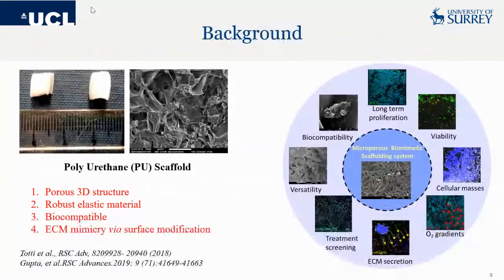So in our group at the University of Surrey and now with UCL, we have developed a polyurethane scaffold-based model of PDAC. These scaffolds are prepared by thermal-induced phase separation methods, and they are highly porous 3D structures. They are quite elastic, they are biocompatible, and we are able to perform ECM mimicry via simple surface-based modification with proteins like collagen and fibronectin.